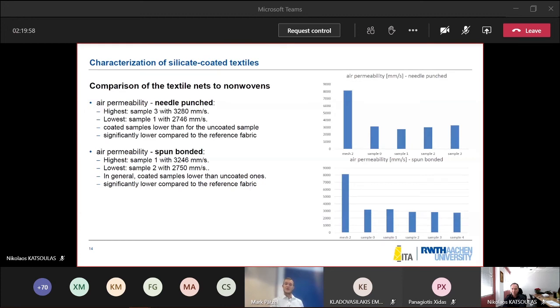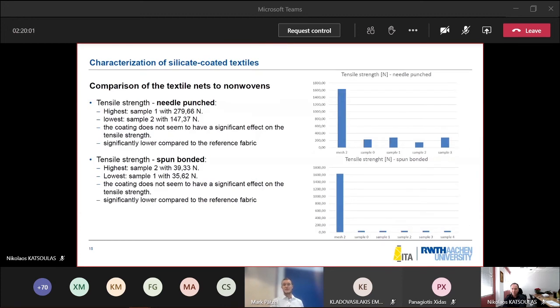The last thing I want to talk about is the comparison of the textile nets and non-wovens regarding the tensile strength. The highest tensile strength is achieved with sample 1 for needle punched and sample 2 for spun bonded, and the lowest with sample 2 for needle punched and sample 1 for spun bonded. It has to be mentioned that the coating does not seem to have a significant effect on the tensile strength, not for needle punched and not for spun bonded. But still, it is significantly lower compared to the reference fabric.